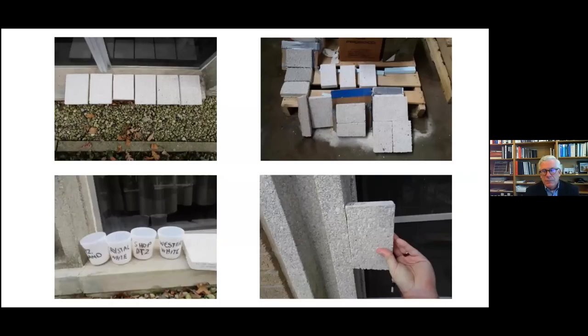And once the appearance was established, the next challenge was to design the concrete mixes and mortar mixes for the repair work. So some aggregate sourcing was performed, many mock-ups were performed, and then revised again, taking into account curing time, aggregate exposure, color changes, surface prep. All these things had to be developed prior to doing any work on the building.